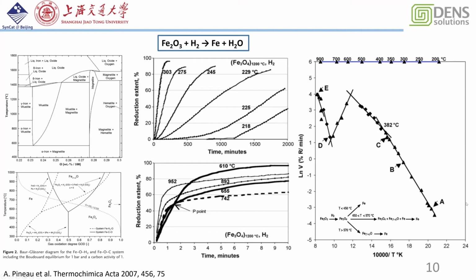And if we use the reduction degree to calculate the activation energy, we can see that the iron oxide reduction activation energy changed at different temperatures. So it's suggested this process is strongly determined by the kinetics, not by the thermodynamics. But what happened in the different reduction processes, and how do we visualize this kinetic process? So we have to use a new technique. In this case, we use the in-situ TEM to do this work.